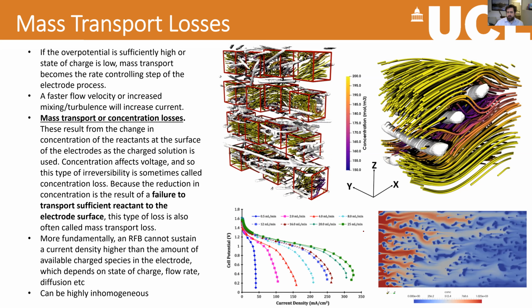You can see here some modeling that we've done on these battery electrode structures, and you can see how we can look at the varying concentration of the reactant depending on its location in the electrode. And as you might expect, in areas close to the active parts of the electrodes where the reactions actually happen, you get a depletion in reactant concentration. And this can happen through the thickness of your electrode as well. So you can see here, we've got a high amount of reactant at the start as it's flowing through the electrode, and then that reactant starts to get depleted. And therefore, when it gets depleted, we start to get these mass transport losses becoming quite significant. And so we end up losing voltage for a particular current density.